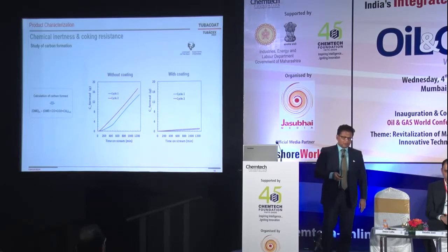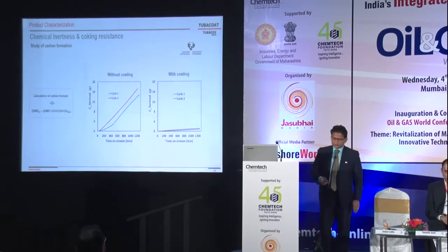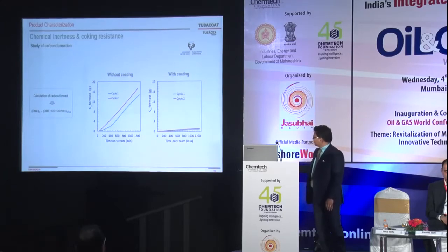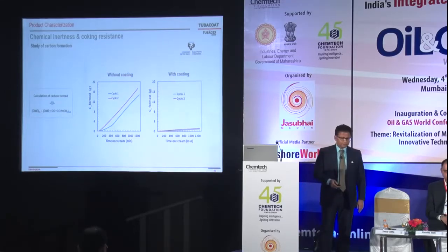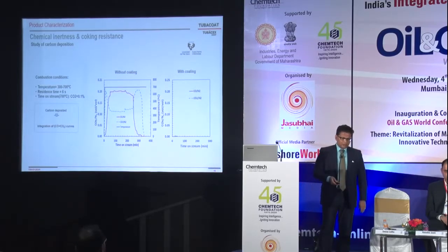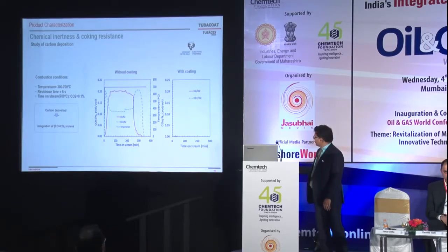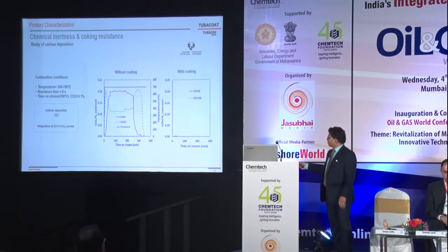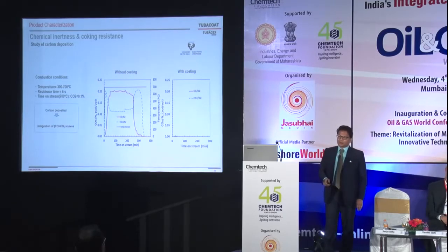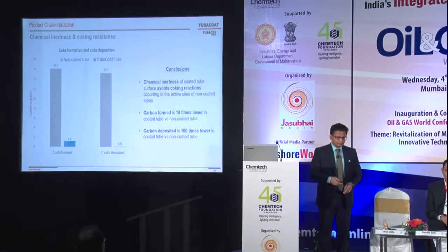So this one is on how much carbon do you form. If you look at this slide, without coating, significant carbon formation, with coating, maybe 10 times lower. And this shows the carbon inertness or the deposition. What you see in this slide is the CO2 measurement curve that shows the carbon deposition because we combust, and this is with the coated tubes, and that is 100 times lower deposition in these tubes.